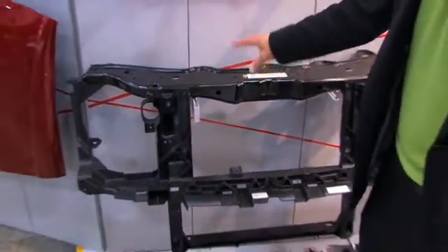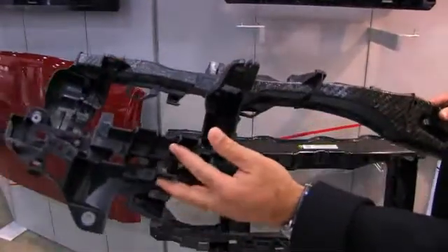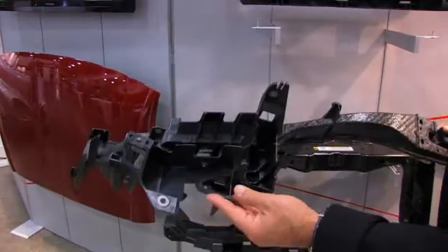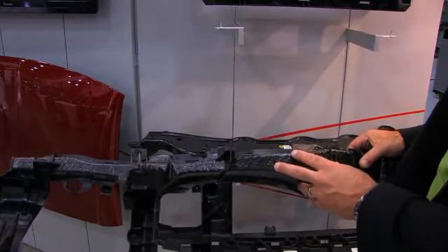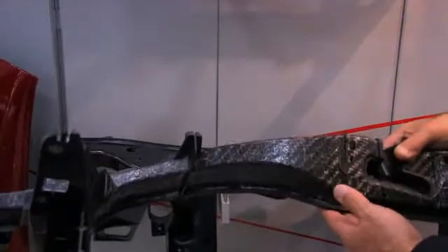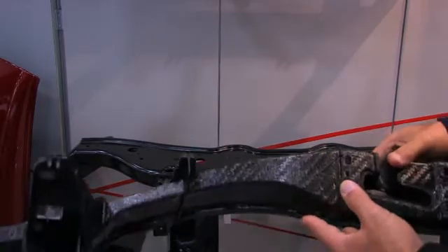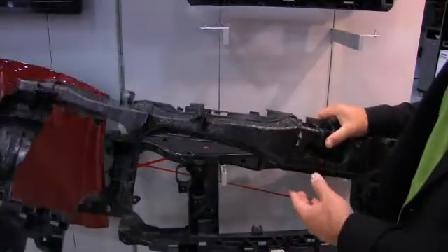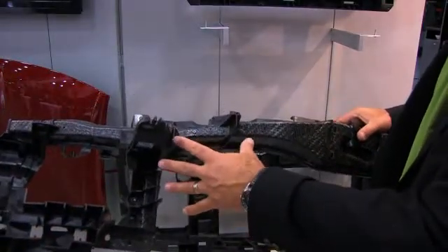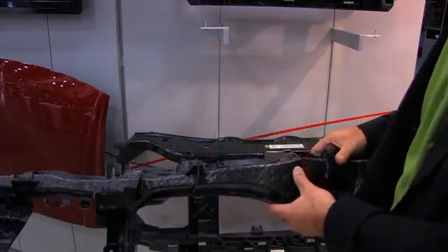This is our Generation 1 front-end carrier, and down below here is the third-generation technology, where we're using a combination of long fibre thermoplastic injection moulding components. The difference now is we're insert moulding or over moulding onto a glass-mat thermoplastic to provide highly-oriented fibre reinforcement in critical areas for vehicle performance, creating an extremely lightweight structure that's a hybrid between random long fibre reinforcement and highly tactical long fibre pre-pregs.